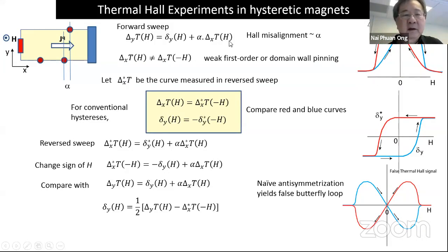So now I'm just plotting what you see when you measure the longitudinal thermal difference along X, sweeping the field from negative to positive, which I'll call the forward sweep. You see the blue curve, and then when you return, you see the red curve, right? And the reason for this is either due to the motion of domain walls, right? Domain walls cause a lag between the magnetization and the imposed field, or it could be due to a weakly first order transition, right? If there's a first order metamagnetic transition, you will always see a lag, right? If you measure the thermal conductivity, you will see this, and that can dominate the intrinsic Hall signal.